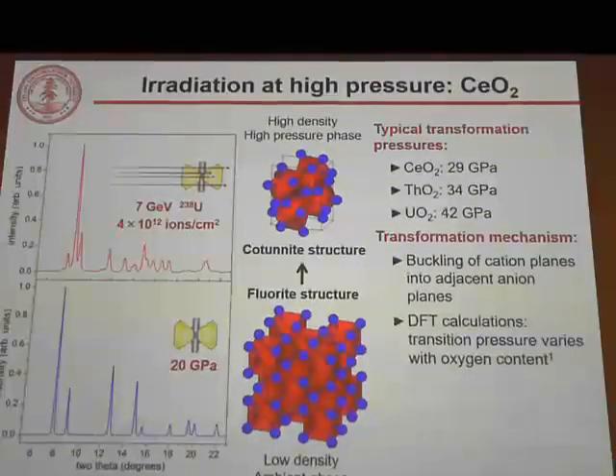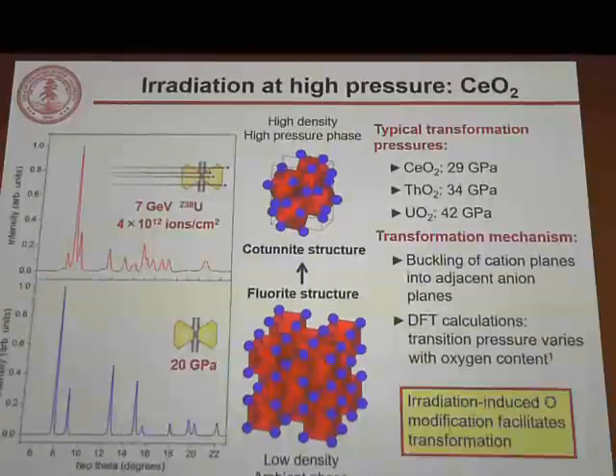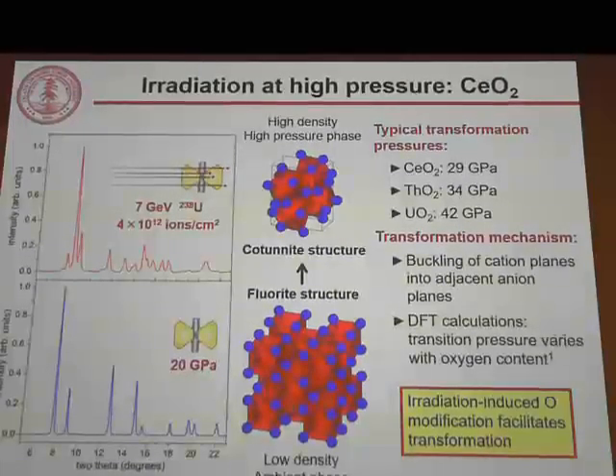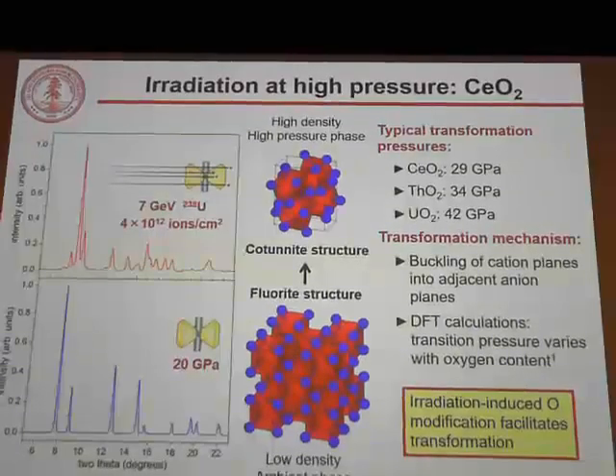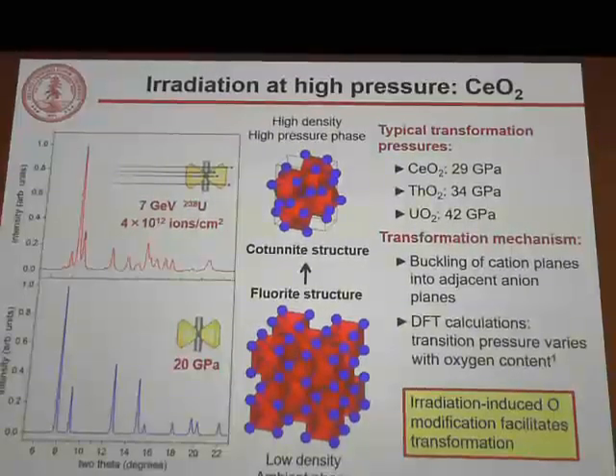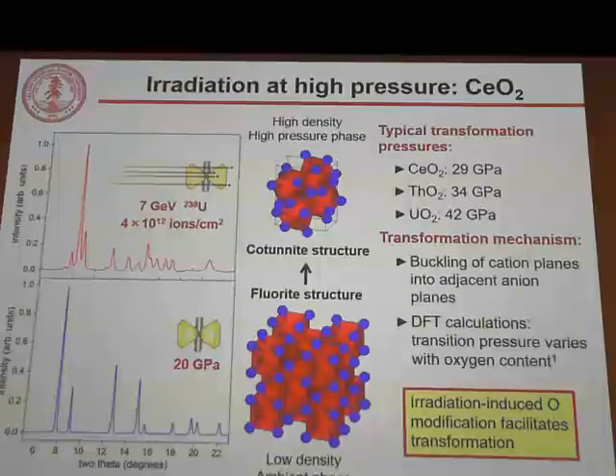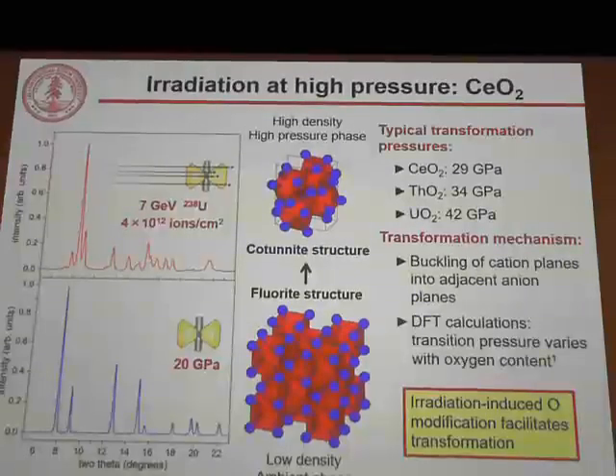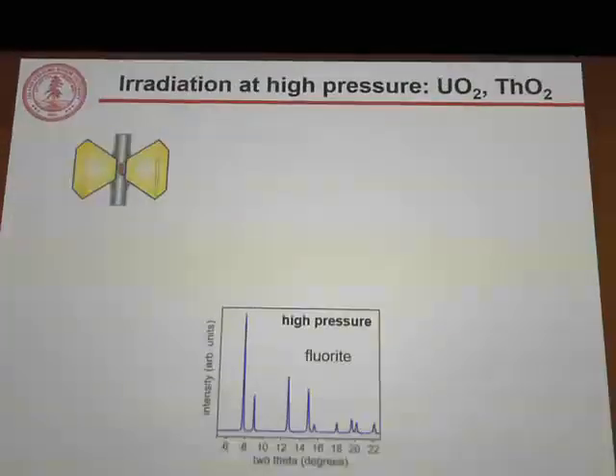In fact, DFT calculations show that the transition pressure varies a lot with oxygen content. So if we now know this irradiation-induced mechanism of oxygen sublattice modification, we understand that it will facilitate this transformation, extending the metastability range of this cotunnite phase to even lower pressures than would be found in the absence of this coupled extreme environment. We've done the same experiments for uranium and thorium dioxide.